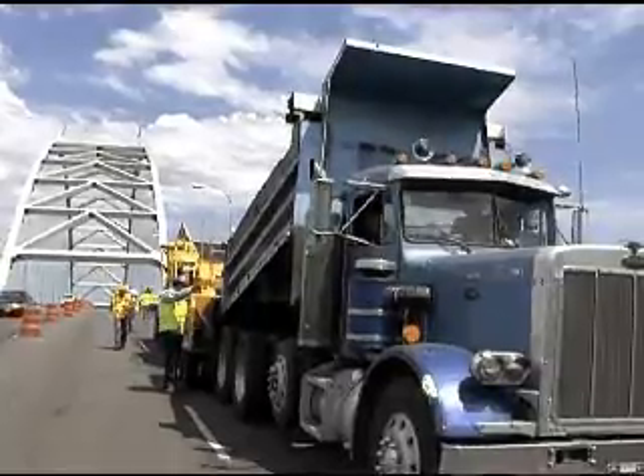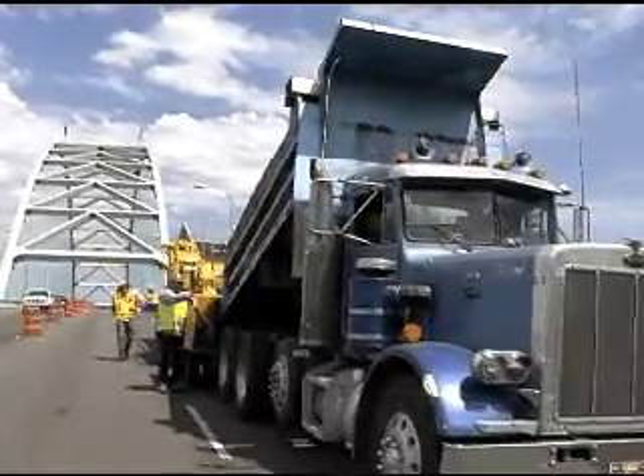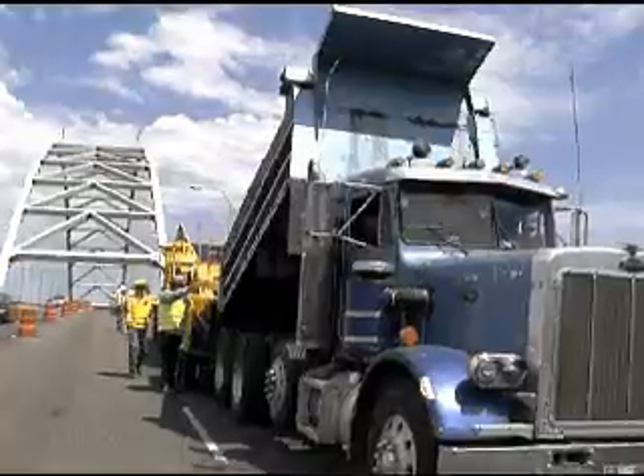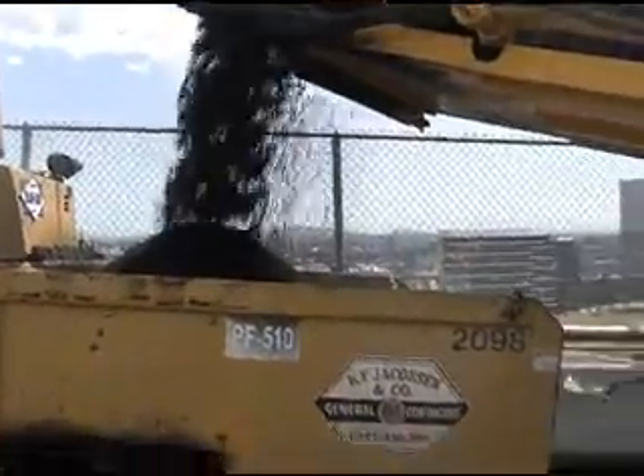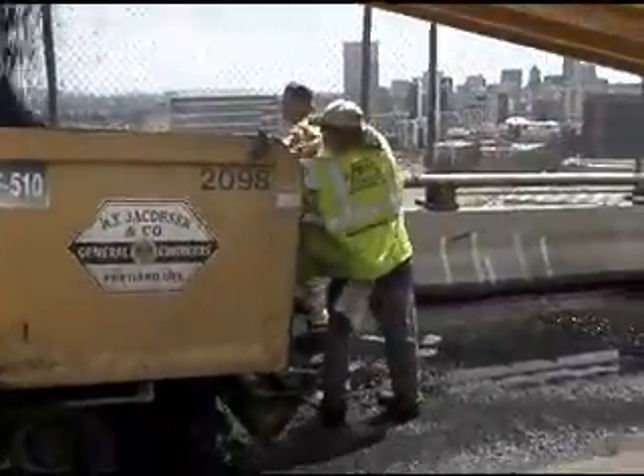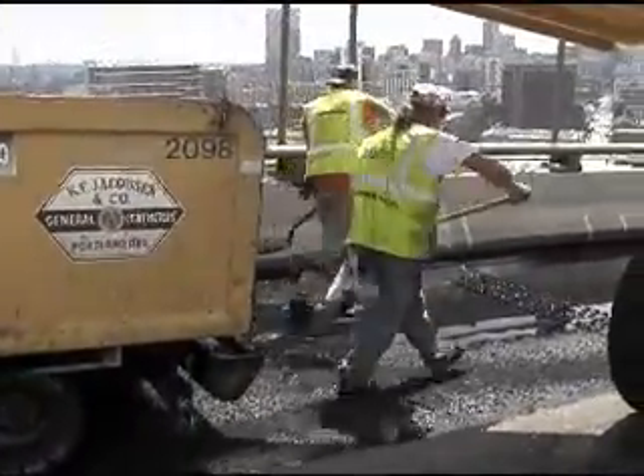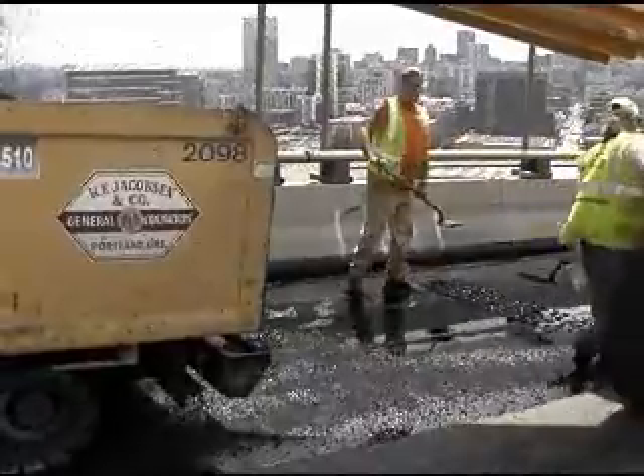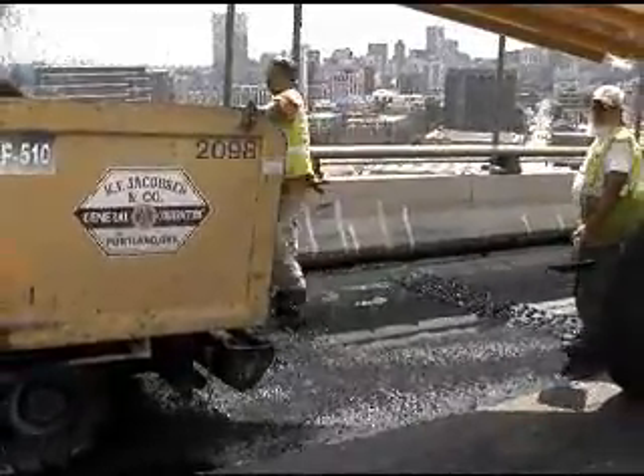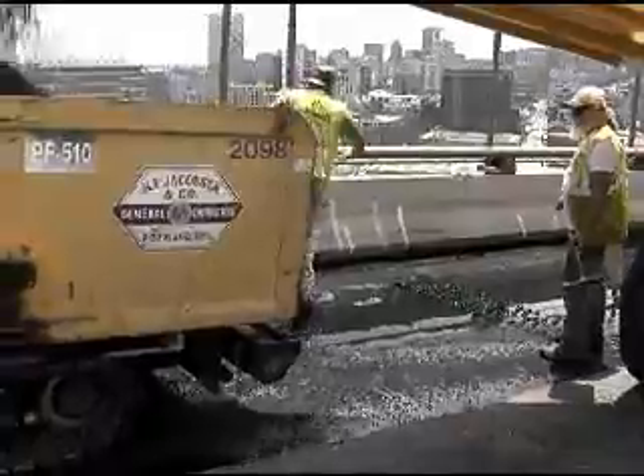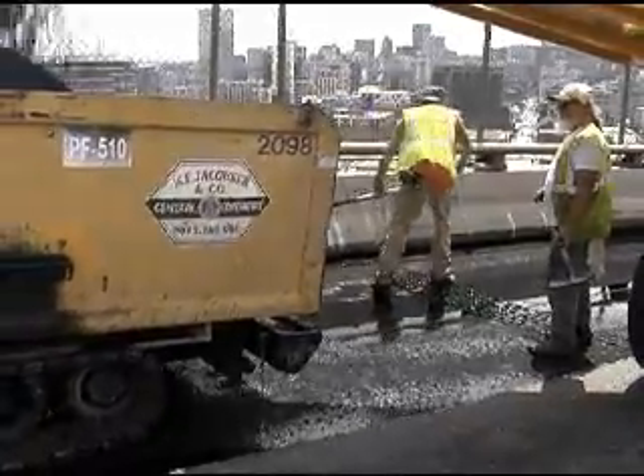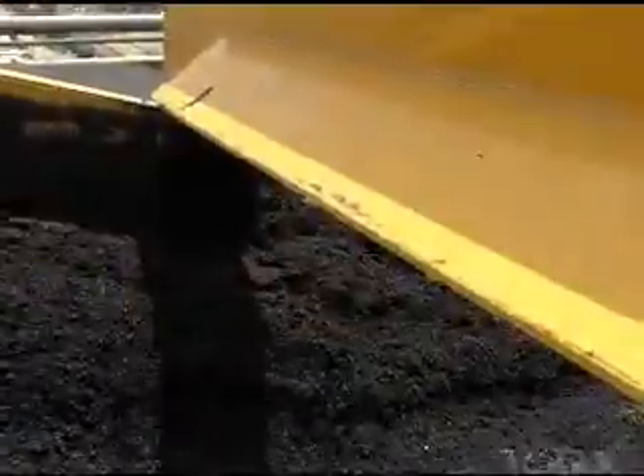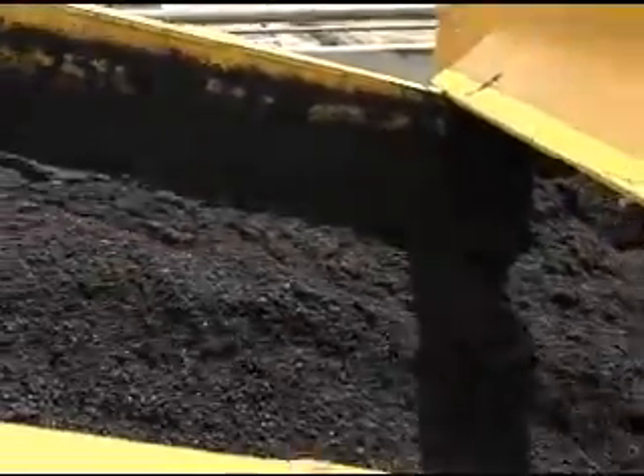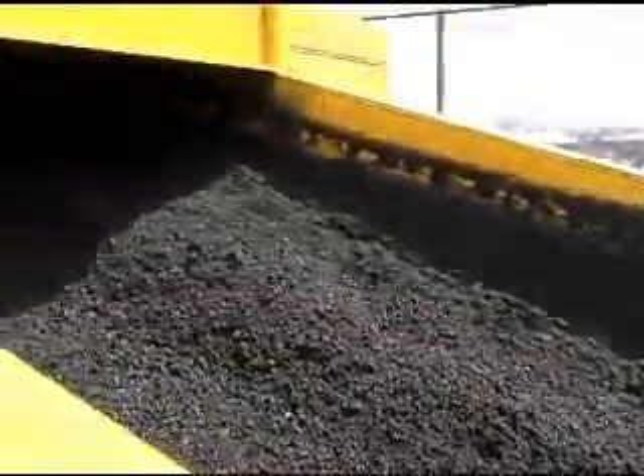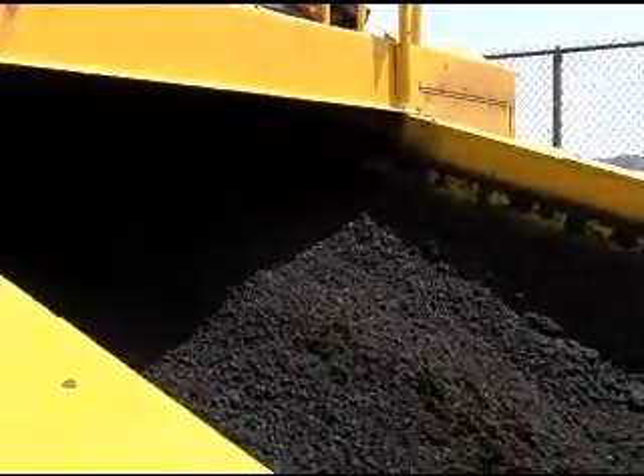Our designers intended for the epoxy asphalt to be placed in 2 lifts. The first lift is a leveling lift because of the bolt heads that stick up on the steel plate. Because those bolt heads stick up on the steel plate, this first course of epoxy asphalt ends up being a leveling course to kind of level out over those bolt heads and make sure we can get a smooth product over those. Then on top of that, we place a top lift to get us to the full thickness that we desire. In this case, our full thickness is 2 1/4 inches. The bottom lift, the leveling lift, is intended to be 1 1/4 inches thick, and the top lift is 1 inch thick.